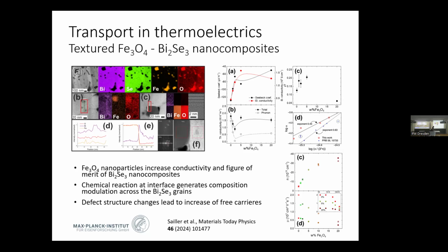Surprisingly, for this type of composite, what occurred in making the composite is that we have a gradient of composition in bismuth. Probably due to an electrochemical effect related to the iron and the oxygen that draws bismuth from the inside of the grains to the part closest to its attractor. And that changed a lot of things. Because we knew the starting bismuth selenide, its chemical composition, structure and defect structure, we could follow the bismuth gradient composition and translate that into defect structure composition. Usually in these materials there is a balance between antisite defects and anion vacancies, which is more or less balanced.